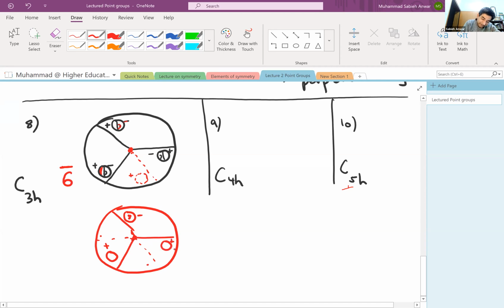But then I get something positive because the negative is going to a positive. This is what the inversion operation does. Something that is below goes above, and the sign is negated in a sense. So likewise, I will construct all of these points that I've drawn. So this point group C3H in the old notation is really represented as 6 bar in the international notation. A threefold rotation and a mirror plane is the same as a six-fold roto-inversion operation, in other words.